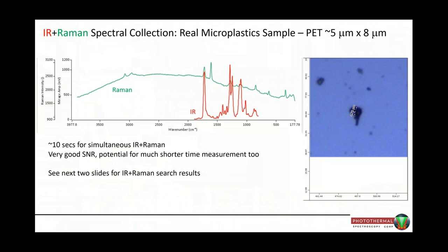This slide shows a simultaneous IR and Raman spectral collection on a real microplastic sample, which was identified as PET. The particular particle is 5 microns by 8 microns in size, and these are the spectra that we collected in the infrared and Raman. It took 10 seconds to collect both the spectra, very good signal-to-noise, and potential for much shorter time measurements.